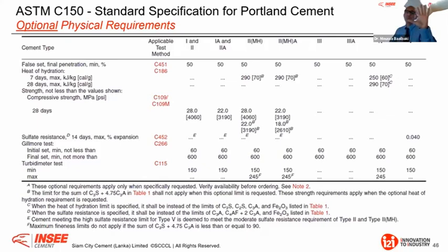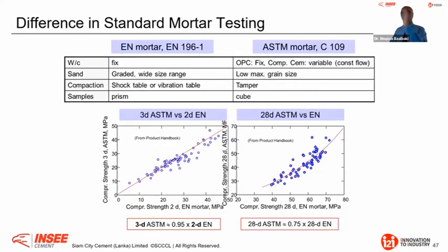That is OPC based. Now, just before I go to C595, I have 2 other slides. One is saying that the difference in standard mortar testing is like the red apple and the green apple. They are apples, but they are different. That is important to know because they do not test in the same way. You know very well the EN is a fixed water cement ratio, graded sand up to 2 millimeter. We use shock table, we use vibrated table, and you have prism.